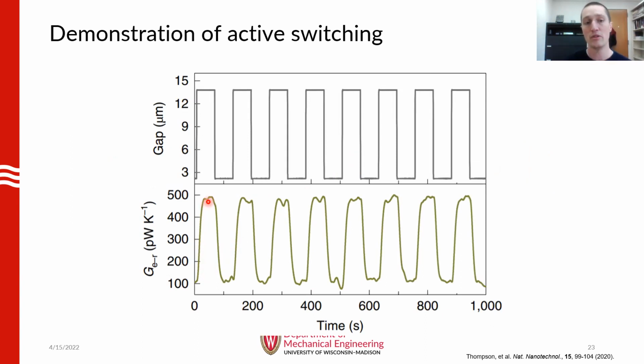I think in principle this switching ratio can be further improved, and I also think the switching time can be further improved. In principle, it's only limited by the thermal time constant of the nanomembranes, which in this case is actually a lot smaller than 2 minutes. It was around 100 milliseconds.